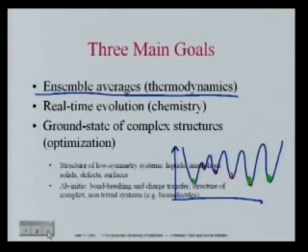Well, we have a problem, because how do we construct the interface between a crystalline solid and an amorphous system? We can try putting atoms in reasonable positions, but it's never going to work very well. And so what we can do is use molecular dynamic techniques to let the atoms evolve according to their interaction and the Newton equations of motion, and somehow find by themselves slightly more favorable minima instead of the initial configuration in which we have put them.